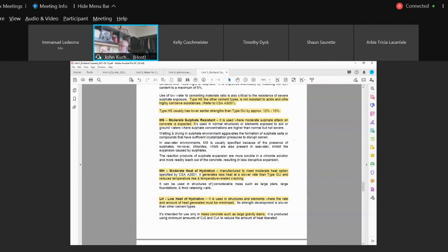You strip that hoarding, in 1 day, what happens? Cracks. From what? Thermal cracking. Not only is your concrete hot on the outside and warm on the inside core, if you had that big element, let's say 3 meters by 3 meters by 3 meters, that temperature on the inside of that concrete, just moving to the outside surface of the concrete, there's a pretty big temperature gradient. Now you're moving it outside to minus 40. So the specifications say that if a contractor is going to remove the hoarding within 7 days, he has to start reducing that internal temperature slowly, such that there isn't a big thermal shock when he takes off the hoarding and bang, you're at minus 40. There are CSA standards for that that give you the amount of temperature drop.